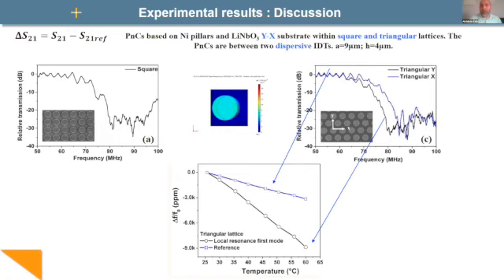lithium niobate. Now, if we test, we can see that the propagation is inside the lithium niobate, and when we go there, the resonance is confined inside the pillars. If we take in the network analyzer the frequency in this region, we will find the characteristic frequency of lithium niobate without pillars. If we consider this position, we will find the characteristic frequency of the pillars and not of lithium niobate.